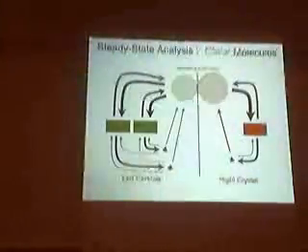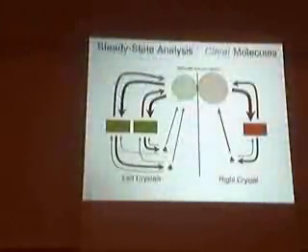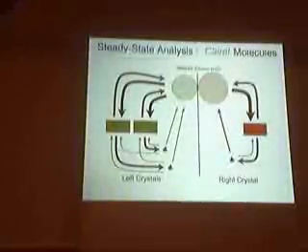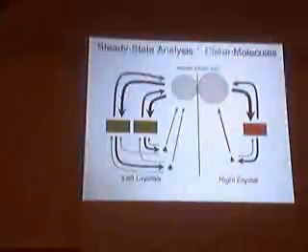You see that we are forming larger crystals, and larger crystals correspond to a lower concentration in the solution. But you don't need that. That's Ostwald ripening, as you say. If you have more crystals of the same size, you also get the effect because there are more ways of trapping the clusters. The more crystals you have of a given kind, the more you can trap the clusters. The more you trap the clusters, the less they dissolve. The less they dissolve, the more solid there is. Yeah, I agree with this.